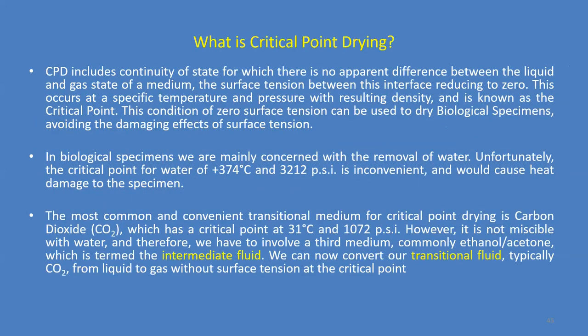So critical point drying is where there is no apparent difference between the liquid and the gaseous state of the medium. The surface tension here is reduced to zero, and this occurs at a specific temperature and pressure with the resulting density known as the critical point. So this condition of zero surface tension can be used to dry biological or delicate specimens, and you can avoid the damaging effects of surface tension.